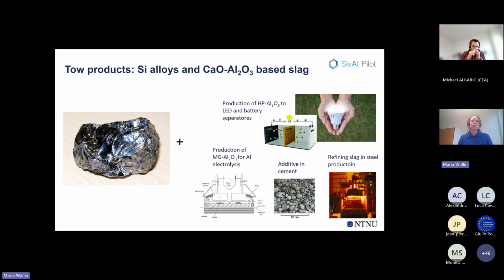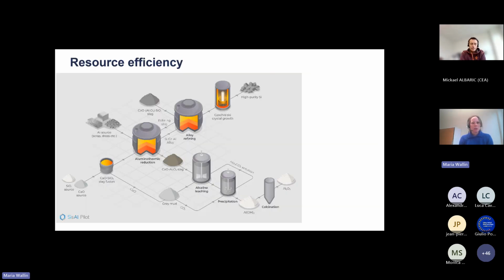So we are looking into a circular process, which you can see here. And in Resilex, here we are. The other part is SisAl, which was done in another EU project. So what we do is that we produce this silicon via the aluminium reduction, and this alloy was metallurgical grade silicon. This is the alloy that we then mix in Resilex with kerf, which is a waste sawing dust from the PV industry, and so we refine our product with the kerf from this other value chain and produce high purity silicon.